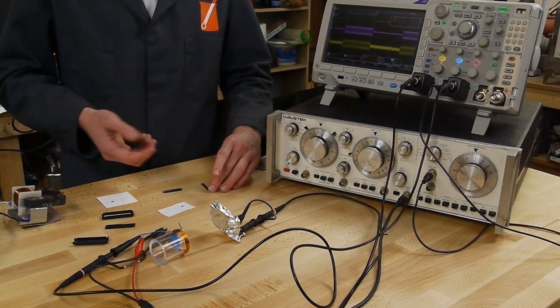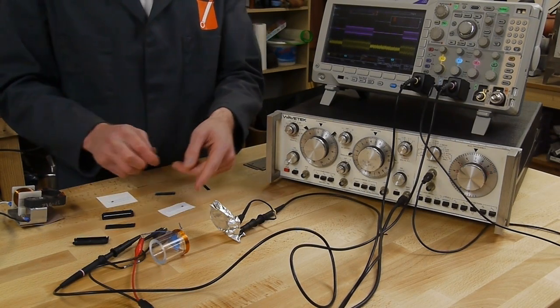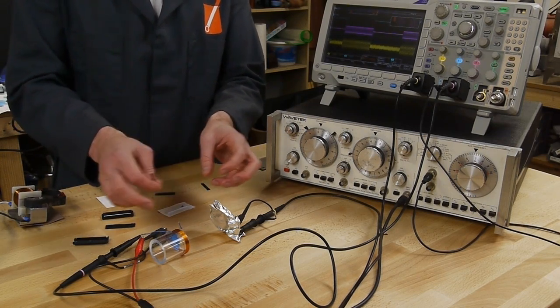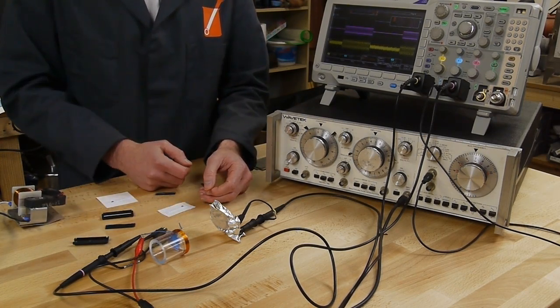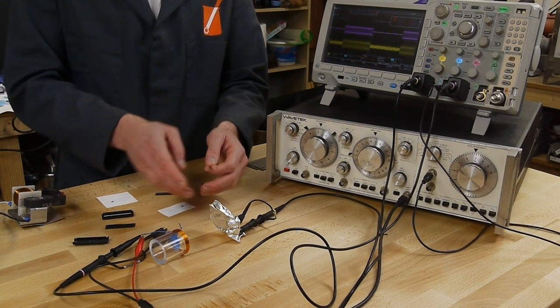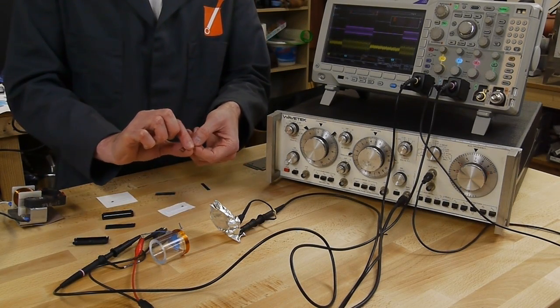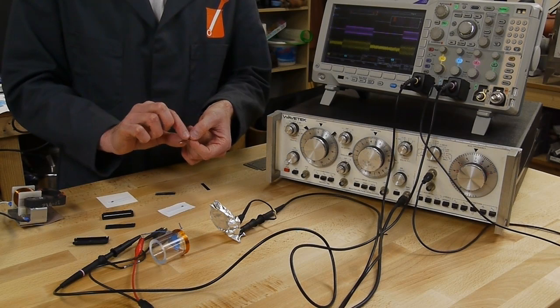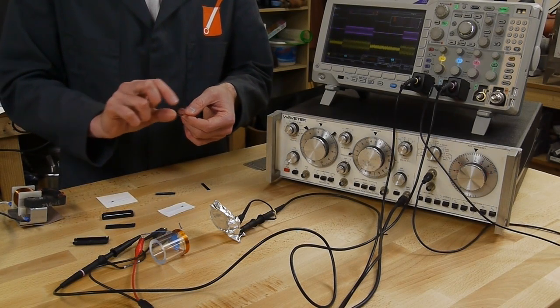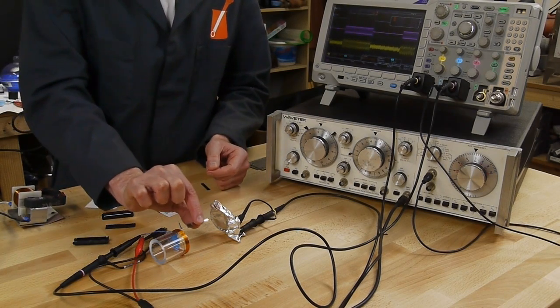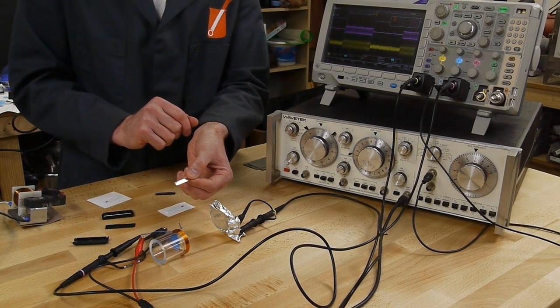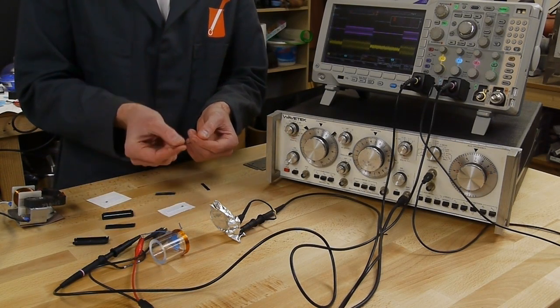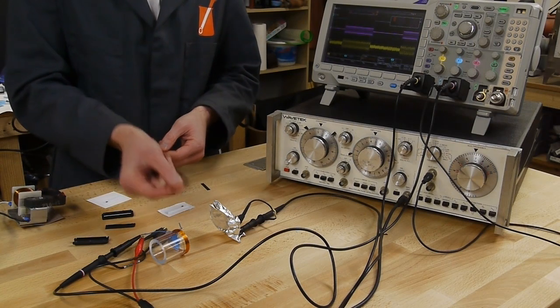So what's actually going on here? The deal is that the transmit coil is creating a very weak magnetic field here. I mean, we're only putting a couple volts or something through this coil. The field being created here is very weak, but it is there, and it's 58 kilohertz, hence the acousto part of this whole thing. If we put the ribbon in here, it will start to vibrate also at 58 kilohertz, and the exact size of this ribbon is critical for how this thing works.